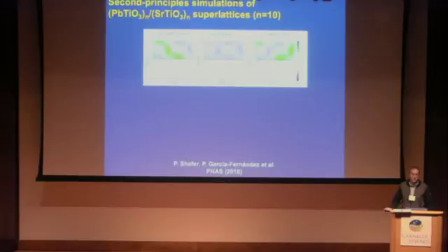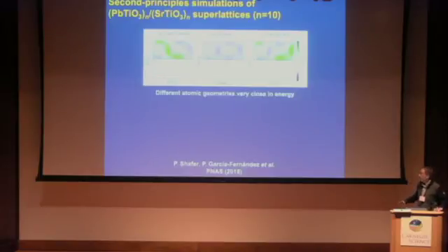So we have carried out second principles simulations on lead titanate, strontium titanate with 10 unit cells of each. And here you have some of the results we are getting. Here the arrows point the components of the polarization in the plane of the screen, and the colors are the component of the polarization perpendicular to the plane of the screen. So green pointing inwards, magenta pointing towards you. So we could identify different atomic geometries that were very close in energy. In particular, the three that I am plotting here are degenerate in energy.